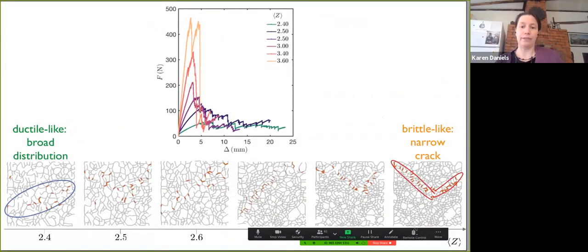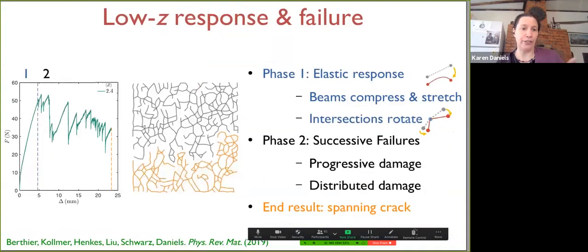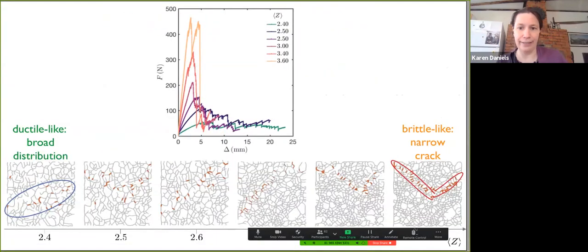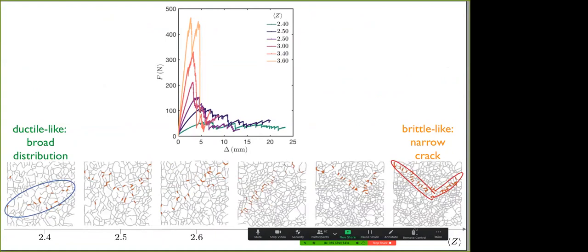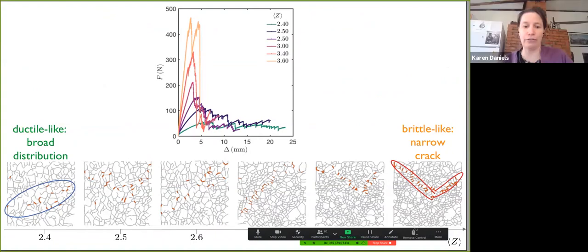If we compare this to what happens, that green line I just showed you, which looked huge, is now the very little bitty green line on here. That was the low Z green example. If we start going through our examples of larger and larger Z, what we see now is much more catastrophic failure. In fact, this orange one at the right loaded up, failed once, and then loaded up again and failed along the other crack. So the whole cracking process took place in 2 steps and 2 steps only. Crack and then crack. This is very brittle-like.